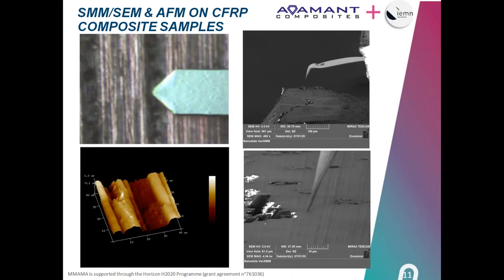Then together with IEMN, Kamel previously presented a nice setup that they have done with SMM and SEM together. And also they have an AFM module there. So we were able to get some nice topology pictures about the roughness of our samples. And then you can see at the right some nice SEM pictures of the probe going to touch our sample.